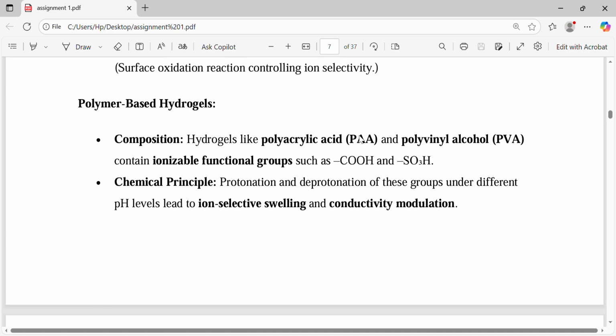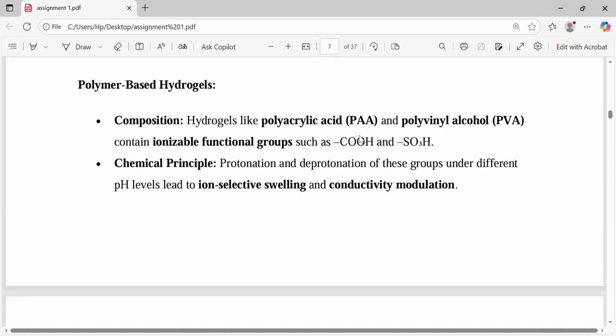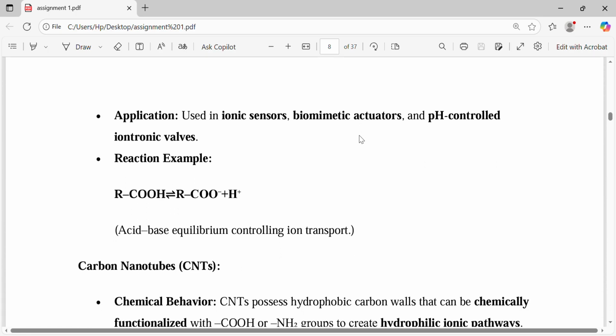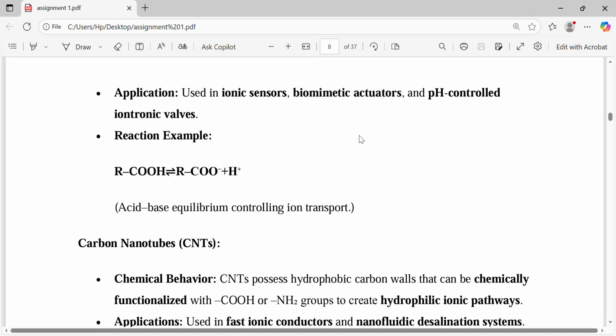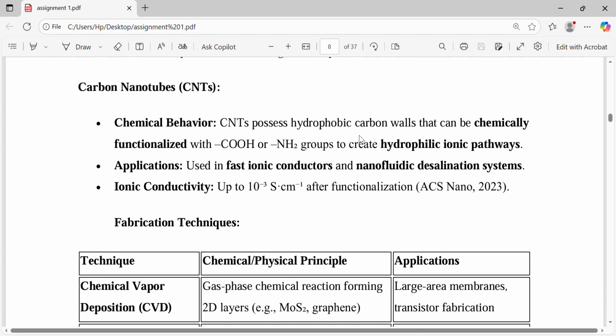Polymer-based hydrogels. Composition: hydrogels like polyacrylic acid and polyvinyl alcohol contain ionizable functional groups such as carboxyl and SO3H. Chemical principle: protonation and deprotonation of these groups under different pH levels lead to ion selective swelling and conductivity modulation. Used in ionic sensors, biomimetic actuators, and pH-controlled ionotronic valves. For example, R-COOH equilibrium with R-COO negative plus H positive. Acid-base equilibrium controlling ion transport.